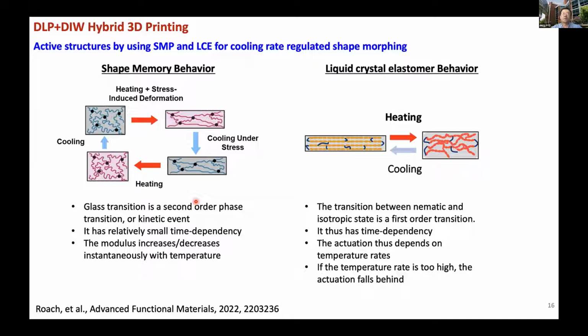Typically we're using the glass transition temperature, right? If you have a polymer that's in the glassy state at room temperature, you heat it up and the polymer becomes rubbery. Then you stretch it, and cool it down while maintaining the stretching load. You change the mobility of your molecular chain, so at temperatures below the glass transition temperature, the chain does not have mobility, and the shape is fixed. If you heat it up again, it just recovers the shape. So basically, the glass transition temperature is a change of the mobility of the chain.